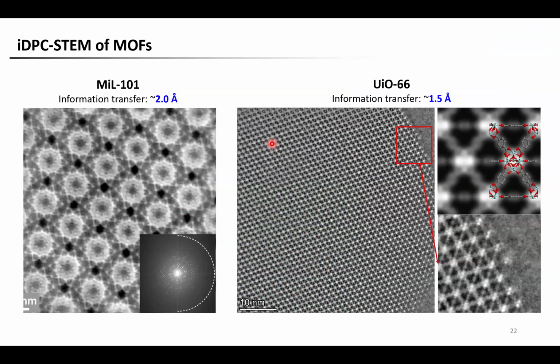Well, zeolites and PTI are considered beam sensitive, but they are not extremely sensitive. So we wondered whether iDPC-STEM can be used to image extremely sensitive materials like MOFs. We gave it a try, and we found that under optimal conditions, it's possible to acquire iDPC-STEM images for some MOFs. The obtained resolution here is already comparable to HRTEM. The advantage here is that the images are nearly directly interpretable. However, I need to emphasize that the success rate of iDPC for MOFs is rather low. This is because iDPC-STEM requires a precisely focused beam to achieve high resolution. When the materials are sensitive, the structure is very likely damaged during the focusing process.